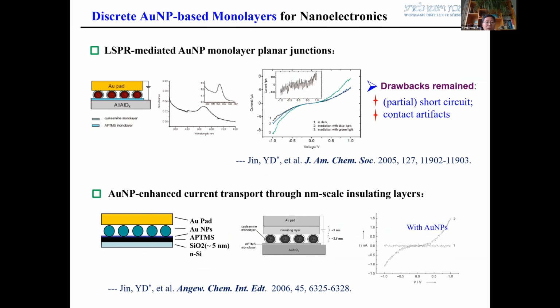Previously, when I was a postdoc at the Weizmann Institute, I prepared LSPR-mediated gold nanoparticle monolayer planar junctions and observed gold nanoparticle-enhanced current transport through about 5 nanometer insulating layers, because of the small organic molecules introduced and also the planar junction configuration used. The result is quite questionable because the drawbacks of short circuits and contact artifacts remain.